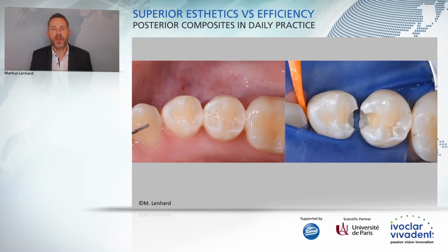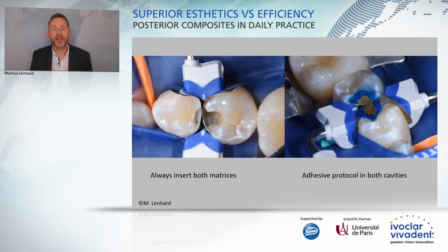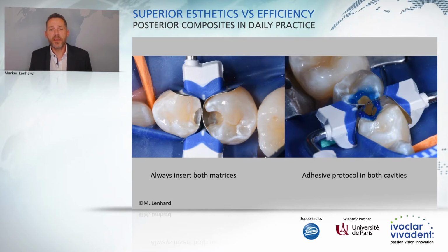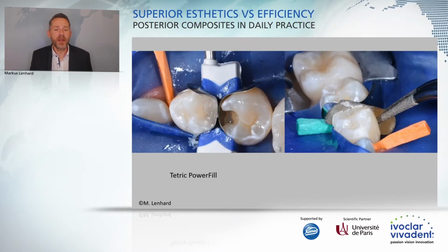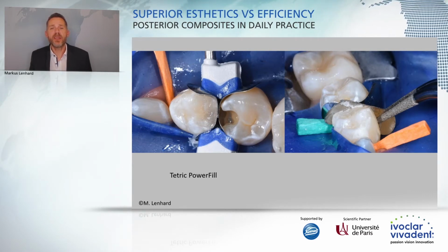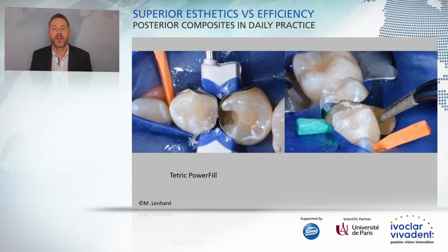And we look here at the initial situation, a small caries that penetrated into dentin, an active caries lesion. On the right-hand side you see the situation after preparation. Now on the left-hand side, the situation after placing the matrix systems, which we will look at in detail again in the longer presentation. Then you do the adhesive protocol with universal adhesives. What you see now on the left-hand side, that's a 1 layer, 3 second cure restoration. As long as the cavity is not deeper than 4 millimeters, you can fill the cavity with just 1 single layer and light cure it in 3 seconds.